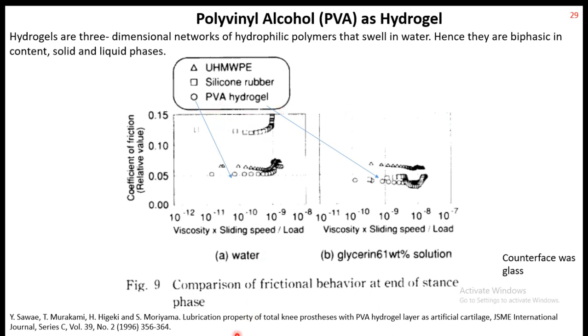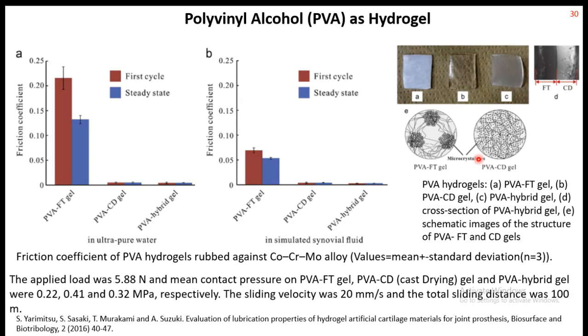For example, quite early on in 1996, PVA was used and some tribology tests were conducted, and it was found that PVA gives a better result compared to UHMWPE when sliding against a glass surface in a simulated lubrication system, in one case water, in another case a glycerin 61 weight percent with water solution. So PVA or hydrogel is being tested by many research groups presently.